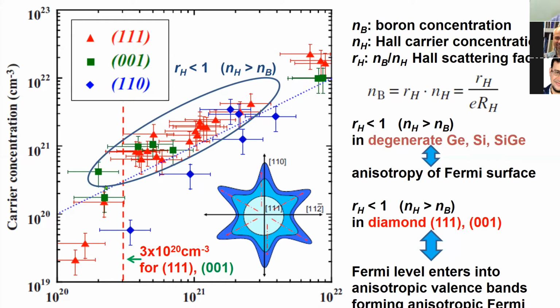What does that mean? Is it an artifact, or we don't know, but this is very reproducibly observed when TC is in high regions. We can explain this as a very anisotropic carrier formation. We and others have calculated that the Fermi surface changes from a sphere, to a little bit anisotropic structure.